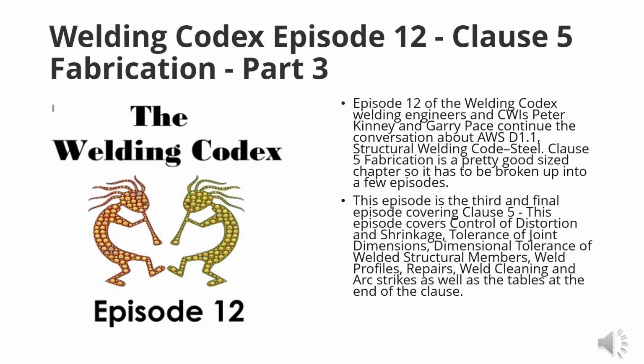Thoughts? In the pipeline world, this was extremely painful. An arc strike could drive a cutout. And it wasn't just an arc strike from the electrode, you could have an arc strike from a ground clamp. So what we would do is grind, or I'm saying grind, but it was more like sanding out the indication. Then we would normally check it by acid etch to make sure that it etched completely the same. That means you've got the heat affected zone gone, or the martensitic area. And then it was either a wet mag or magnetic particle tested. Dye pen could also work. And then we had thickness checks on top of that, because you were making the wall thickness thinner and you had a level that you couldn't go below. So arc strikes can be serious business depending on what industry you're in.